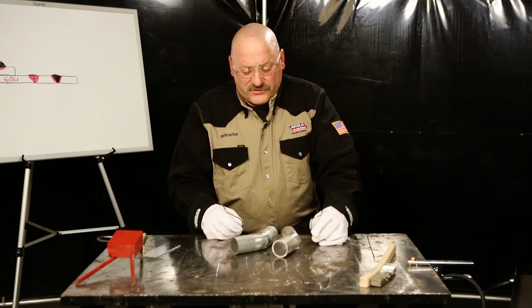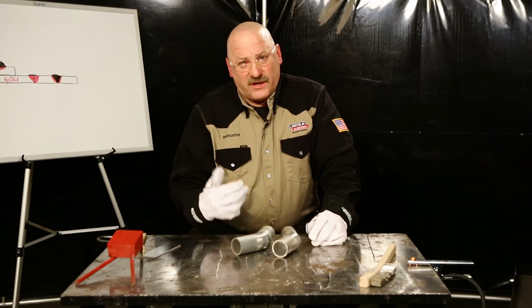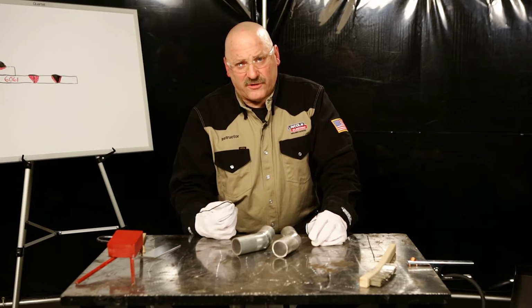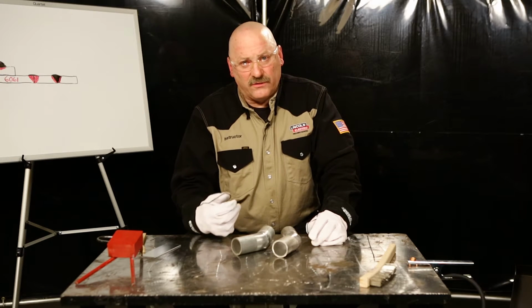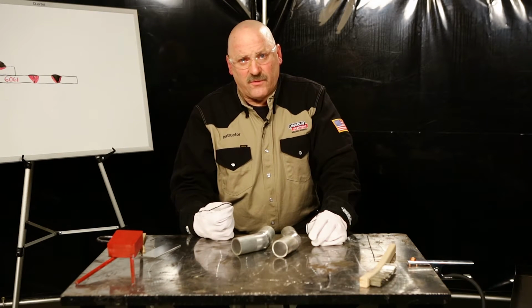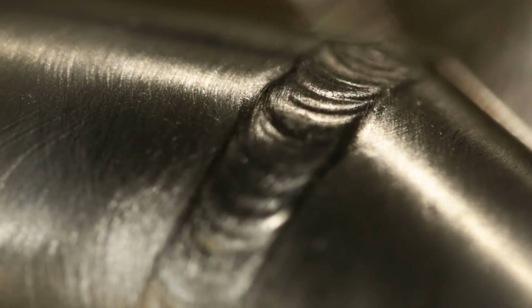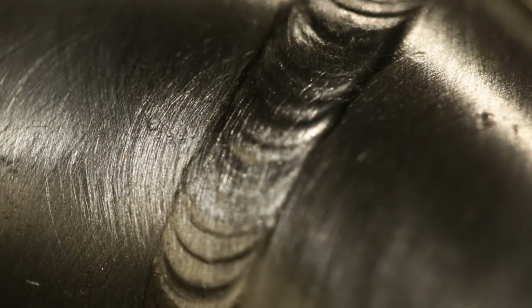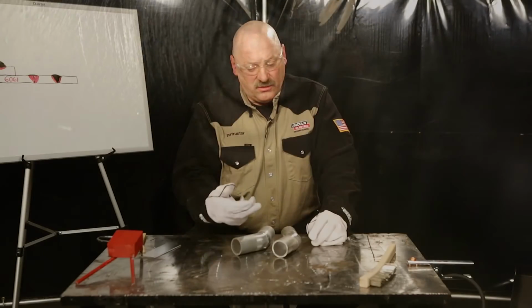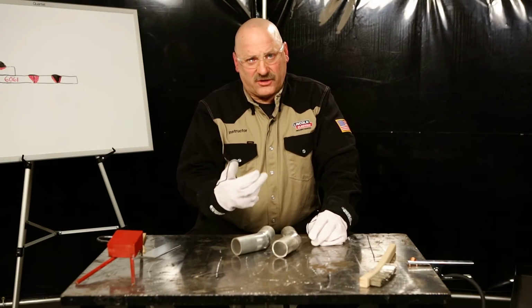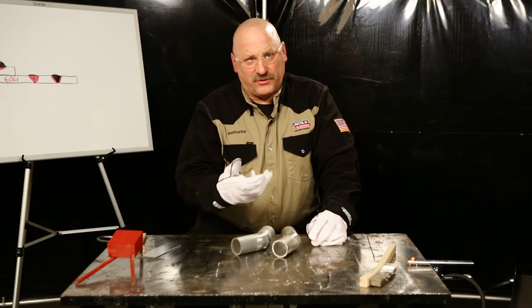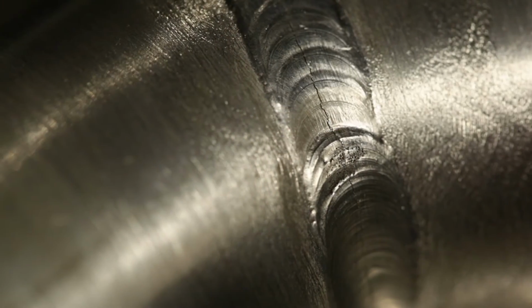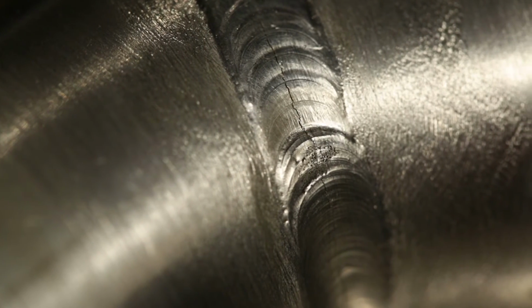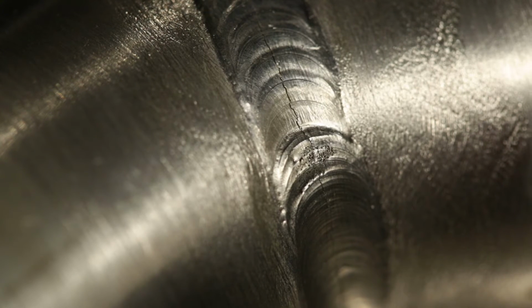So the key to welding 60 series aluminum is to make sure that we get plenty of filler metal of a different composition into that weld. 6061 aluminum is very weldable if it's welded properly. With the beveled joint, I'm able to get more filler metal in that weld deposit than I have base metal. When I went with the square groove weld, I penetrated down into that base metal and melted all that base metal, added very little filler metal. It's resulted in a solidification crack down the middle of that weld.